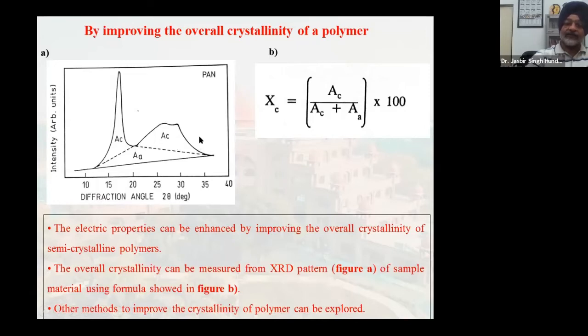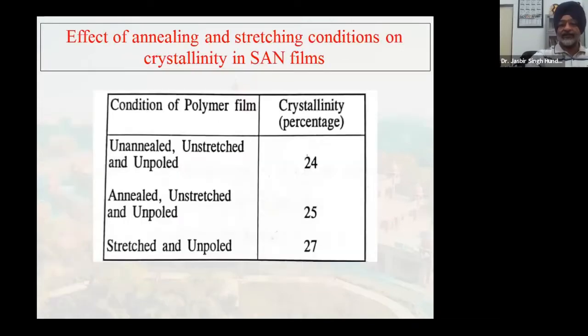So this area AC by AC plus AA, the total area under the peak, that is under the amorphous region plus the crystalline region. So that gives you area under the crystalline region versus the total area under the two peaks. That gives you percentage of crystallinity. Interestingly, even crystallinity affects the D31 and TSC studies. So this is the crystallinity that improved just by 3%, not much.